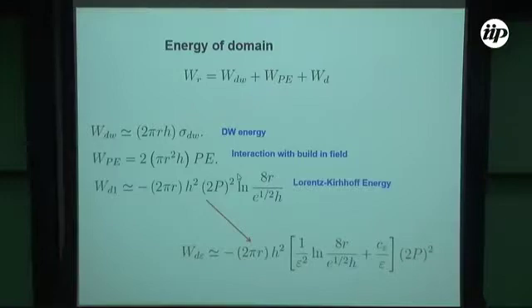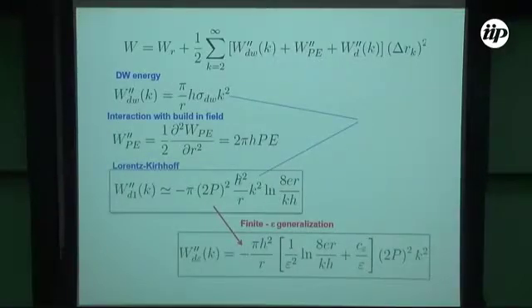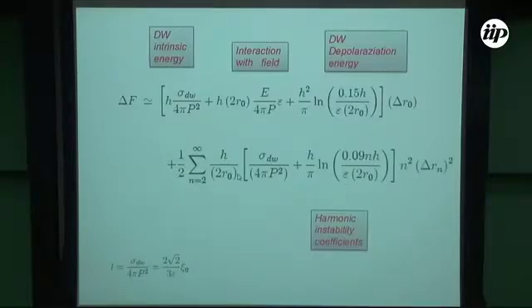Pasha is away. So we consider WD as the Lorentz-Kirchhoff energy. PE is the interaction with the electric field, because there was also some internal built-in field. And what does not come from electrostatics is the domain wall energy, with just some given number. So when we put everything together, after we completely repeated the Tilley consideration for this kind of instability and recalculated all of the terms, trying different harmonics, possibly it's even better here. I don't know which formula is better. And finally, we find the correction coefficients for all of the harmonics. This is the mathematical formula that we obtained.